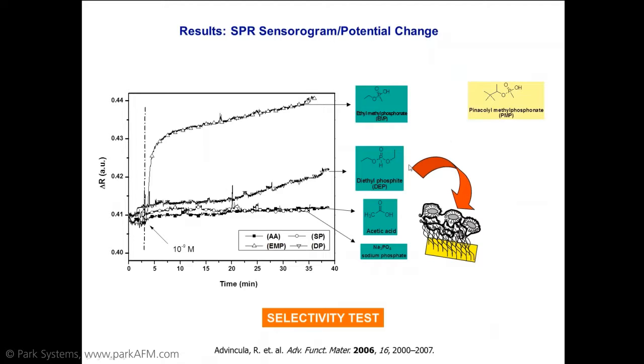So for example, if we take the PMP, which is this, we try to detect EMP, which is not very far from PMP, we observe a similar response or closer to PMP. However, if we use DEP, acetic acid, or sodium phosphate, the response is low. In other words, this system we built is quite particular with PMP and EMP. And so if we test it with vinegar or any inorganic phosphate, it doesn't show a good response. So the selectivity test actually shows that it's quite selective for PMP, and its closer analog called EMP.